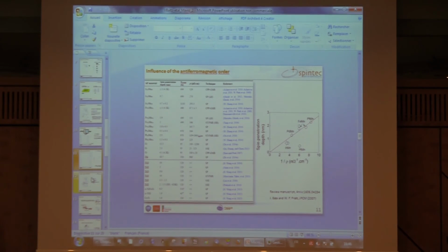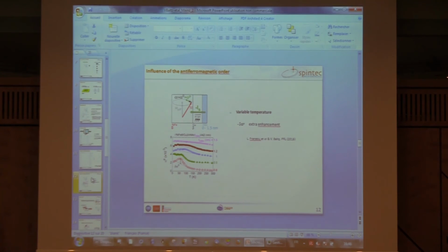You were not able to measure the Néel temperature above 1.5 nanometers for some reason. Yeah, in here. Actually, in this case, the amplitude of this delta alpha P seems to decrease when the temperature increases. So if we have a look at the theory by Onuma and his co-workers, there is a surface to volume prefactor before the susceptibility. So in this case, when we increase the volume of our material by increasing the thickness, we reduce the amplitude of the peak. So you lose the sensitivity at these higher thicknesses. Yes, absolutely.